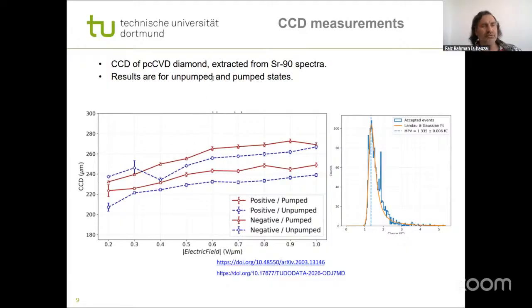So we have a 500 micrometer thick diamond, but the charge collection distance is only 260 or up to 280 micrometer. It means that we lose almost half of the electrons during the signal drift. Not many of the electrons or holes reach the electrode to be detected, as in a full drift. So this is the effect of these grain boundaries that we see here for electrons and holes, both for pumped and unpumped state. Pumping is to fill these traps, but not all traps, only part of them, by irradiating it with a beta source.